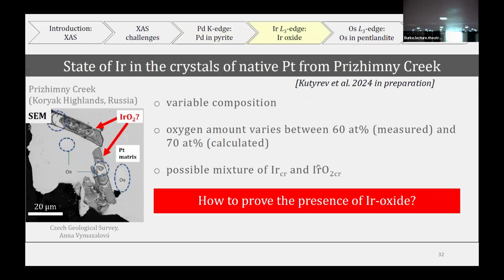The next example is an experiment at the iridium L3 edge. This sample was collected by Anton Kutyrev. It is a native platinum, which contains micro-inclusions of something that Anton Kutyrev wanted to check. They measured their composition by microprobe, however their composition was quite variable. So they wanted to be sure whether they have iridium oxide, which nobody found before in nature, or not.